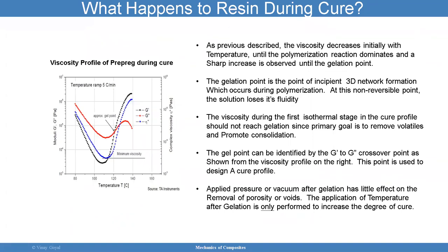So what happens to the resin during cure? As I described previously, the viscosity decreases initially with temperature. So as I increase temperature, viscosity decreases, until the full polymerization reaction dominates, and a sharp increase is then observed at the gelation point. Okay, so you're going to see a gelation point right here. So a decrease in viscosity and then an increase there.